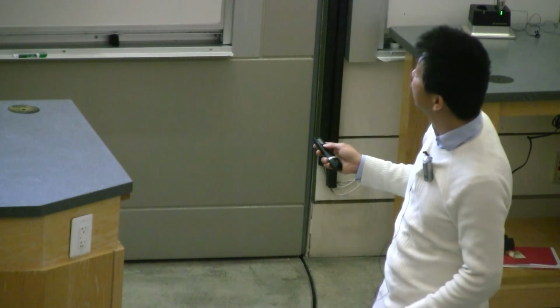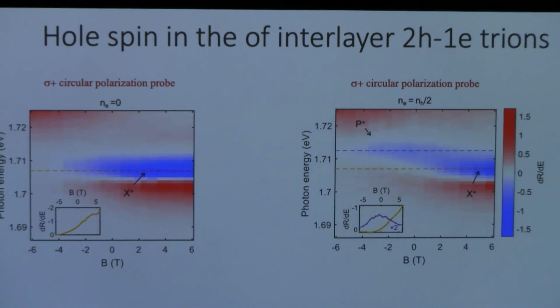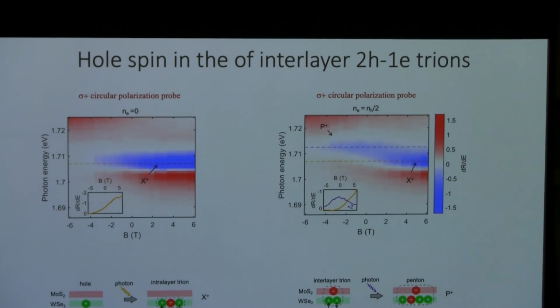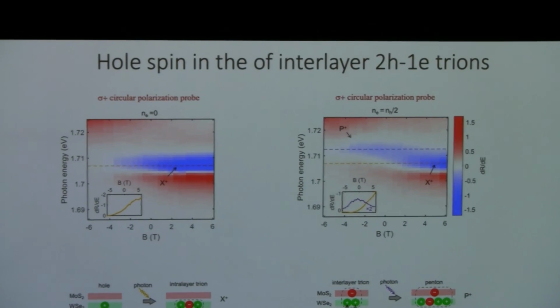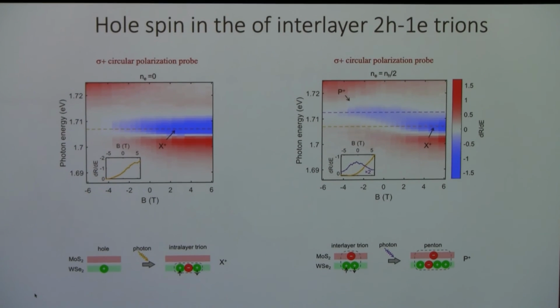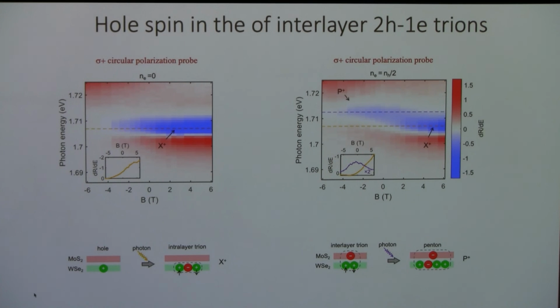Because we are only probing the one layer, what you can see is this type of thing. The spin of the holes will affect the spectrum strongly, because you are creating excitons in the WSe2 layer. So it will be very sensitive to the spin configuration of the holes present in this layer. The electrons don't contribute to these optical transitions, so they don't really play any role. If you want to ask whether the electron spin affects the formation of the interlayer trion itself, it also doesn't matter, because the electron is in a different layer, so there is negligible exchange interaction.